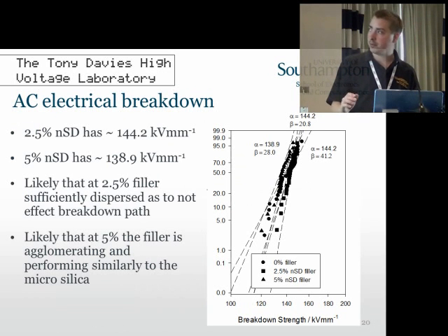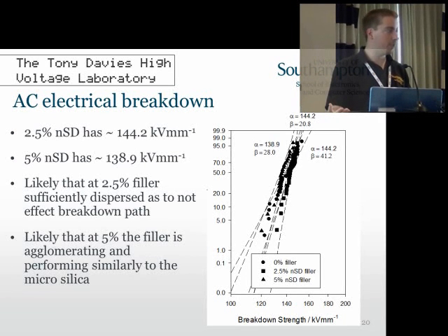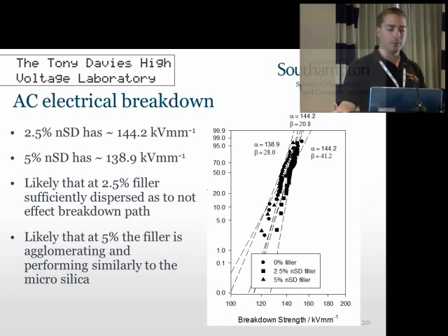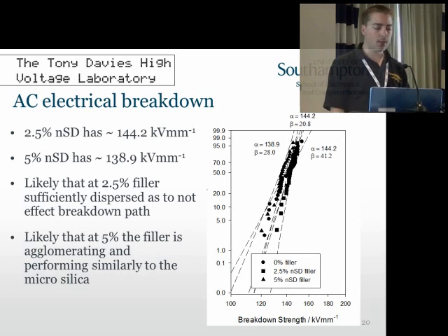So moving on to the nano systems, with addition of the 2.5% by weight, we actually saw no change in the breakdown strength. The graphs are a bit clumped together, but you can still roughly see what's going on. Obviously, this is likely due to the fact that it's dispersed enough that the nanoparticles aren't really acting as jumping sites as the breakdown proceeds through the sample. So this suggests that we've actually managed to disperse the filler to an acceptable level to not compromise the insulation properties of the material. However, once we add 5%, in a similar way to the microsystems, we do see a decrease in the breakdown strength. Again, this is likely to be the agglomeration effect occurring because our dispersion method isn't the best. And the agglomeration is going to cause the materials to behave more like the microsystems, in that we'll have the breakdown jumping across the fillers when in the matrix.